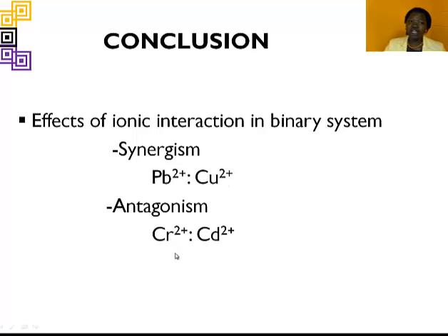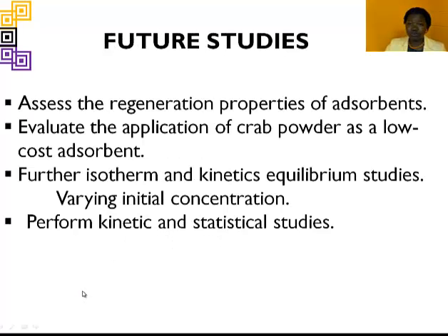On the other hand, antagonism represents inhibition, whereby we have competition for active adsorption sites, and this was experienced in our chromium to cadmium binary system. This is due to the formation of non-adsorbable complexes, and that will lead to an antagonistic reaction.